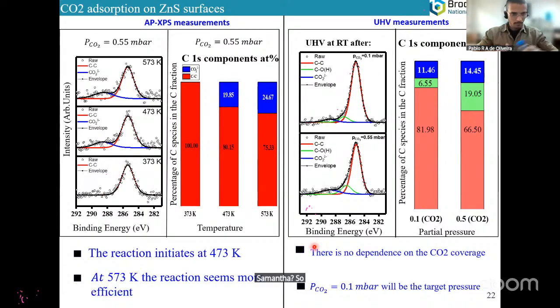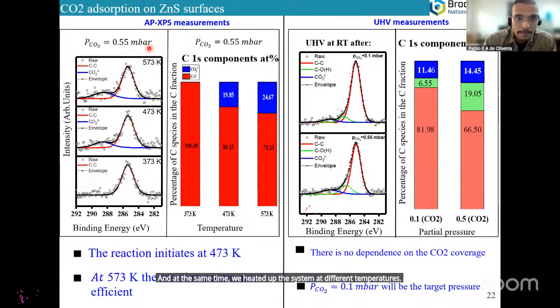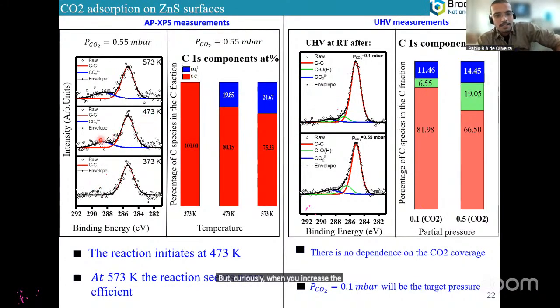So, starting, we exposed the ZnS sample to a CO2 pressure of 0.55 millibar. And at the same time, we heated up the system to different temperatures. So this is the operando condition of the system. And we note that at 373K there's no satellite peak on the left, but curiously, when you increase the temperature, these peaks start to rise and become broader at 573K.